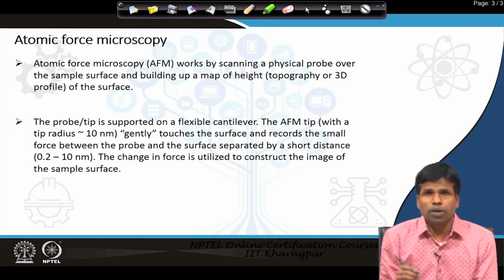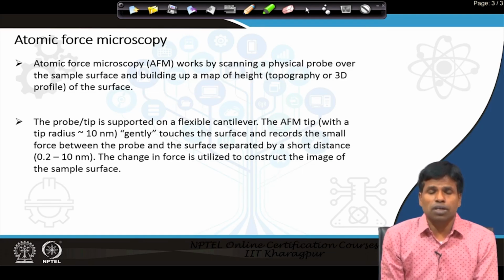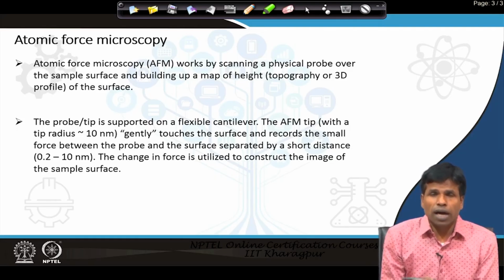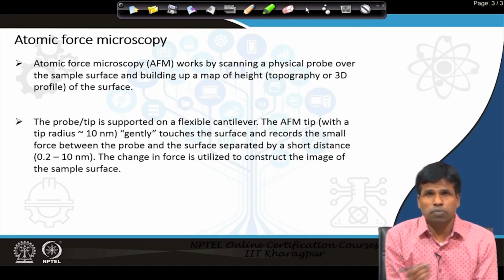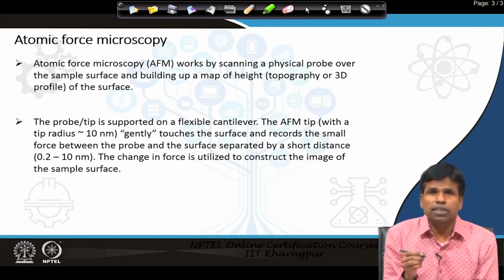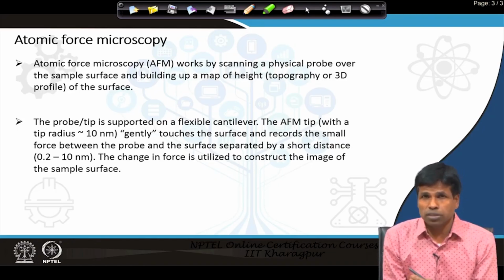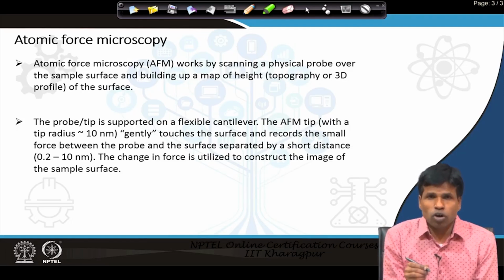the sample and building a map of height, or a 3D profile of the surface. It is done by taking a tip with a radius of around 5 to 10 nanometers. Unlike in the previous STM case, the tip does not have to be a single atom. Here the tip can be a little bigger, and the tip touches the surface and records the force between the tip and sample. So, the force is measured between a few atoms at the tip and a few atoms at the surface, and that force is utilized to create the image.